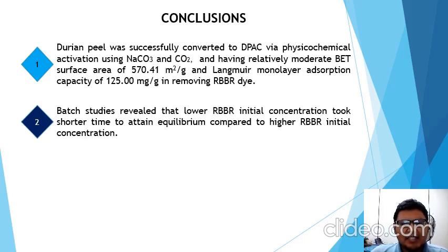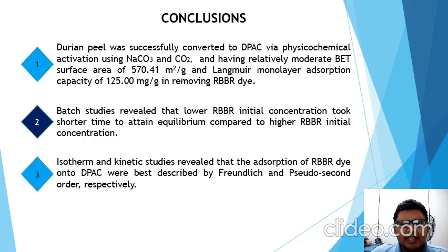Secondly, batch studies revealed that lower RBBR initial concentration took shorter time to attain equilibrium as compared to the higher RBBR initial concentration. Thirdly, isotherm and kinetic studies revealed that the adsorption of RBBR dye onto DPAC was best described by Freundlich and pseudo second order respectively.